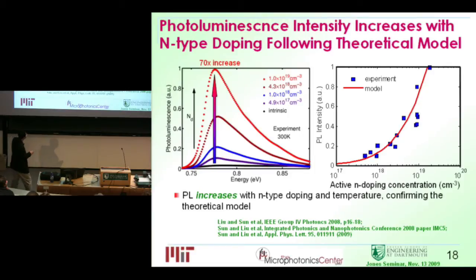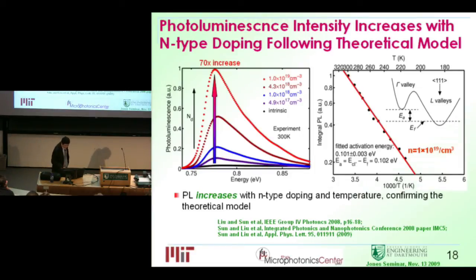They agree pretty well. And another interesting feature is that the light emission intensity actually increases with temperature. For those of you who are familiar with III-V semiconductors, it's usually the opposite way in III-V. So you don't want to operate at high temperature. But here, thermal excitation is actually promoting electrons from this bottom to this bottom. So that's why you get an enhanced light emission at high temperatures. We have gone up to 80 degrees C, and this intensity is still growing. So that means it's pretty robust to thermal fluctuation on chip.